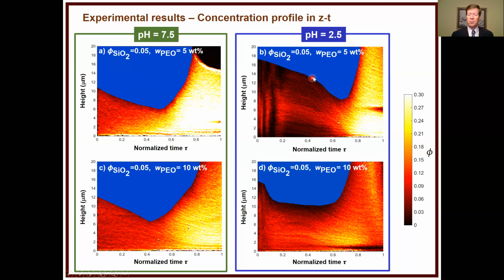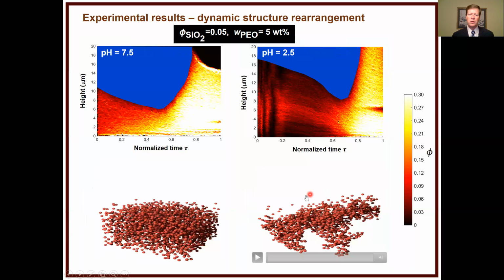In contrast, at pH 2.5, we see very drastic fluctuations in concentration. You can think of this as the concentration going up and down, up and down. What's happening is there is a gel that has a microstructure and you're sampling different points of that microstructure at different times. If I showed you 20 experiments, all of them look different in this initial time. Then eventually things become more uniform again and very concentrated. And again, at a higher weight percent of PEO, you have initial fluctuations, and then eventually you'll see a concentration of the film.